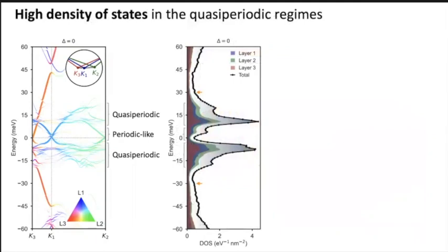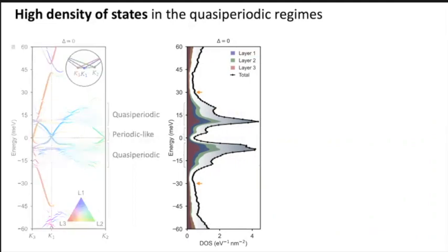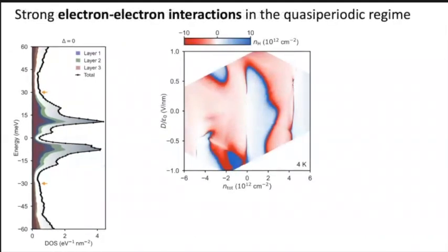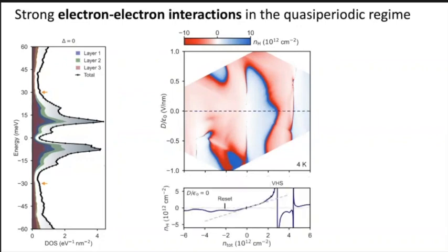Now, in this system, you can calculate the density of states. As you can imagine, this region of flat spaghettis of quasi bands gives you a very high density of states. When you now measure the Hall density of the system as a function of displacement field and density, there is a lot of information here. I encourage you to go to the paper if you want to know more details. Basically, this type of analysis of the Hall density was done in the magic angle trilayer case to determine the presence of van Hove singularities and Fermi surface reconstructions, which lead to a reset of the Hall density, which some people spoke about yesterday. But if you take a trace here, your Hall density versus the gate-induced density should be a straight line.